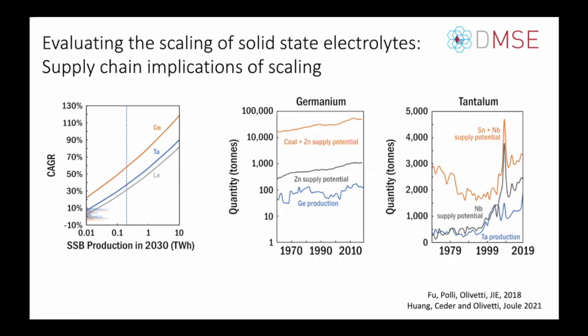As well as on the right hand side, tantalum is also extracted as a byproduct material, similar to the way cobalt is. In tantalum's case, it's from niobium and tin. And so what I'm plotting over time here is tantalum production relative to the potential for added tantalum capacity relative to extraction of niobium and tin. And we see that this is the production buffer associated with tantalum relative to these other elements. And as you compare to germanium, which is log scale here, we're very much below the buffer for current germanium production, it's not so true for tantalum.